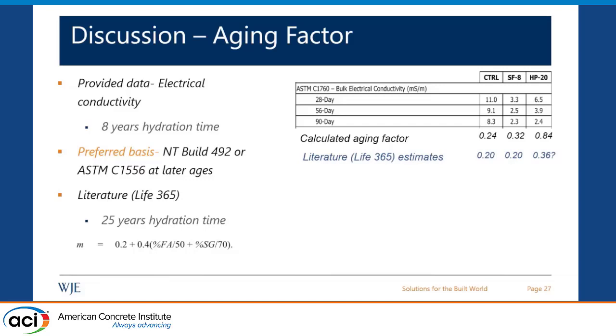Life 365, or the data actually presented in the literature and summarized in Life 365, assumes 25 years of hydration time. The testing that was done to produce this data looked at chloride profiles at different ages up to 25 years. And conservatively, they capped the hydration time to that value, to the 25 years. And they came up with a correlation, based on the data they have seen, of what the aging factor would be as a function of the percentage of fly ash and slag in your mix. And conservatively, they capped that value at 0.6.